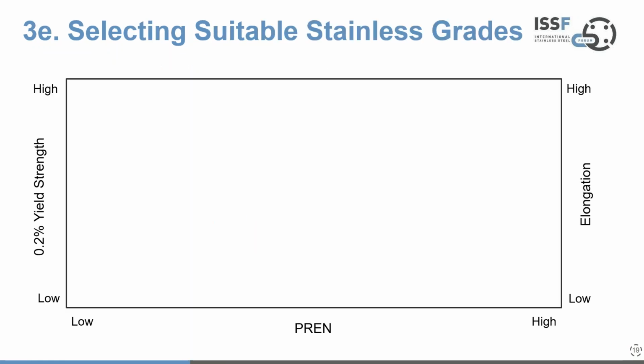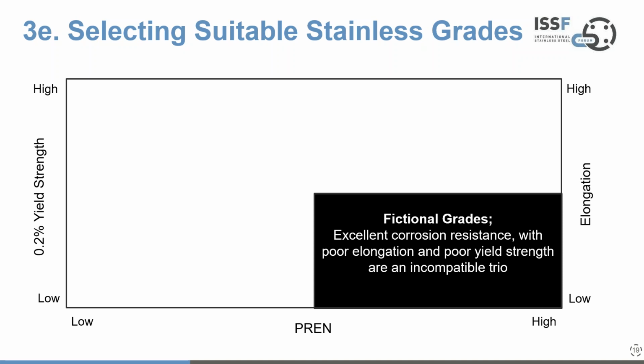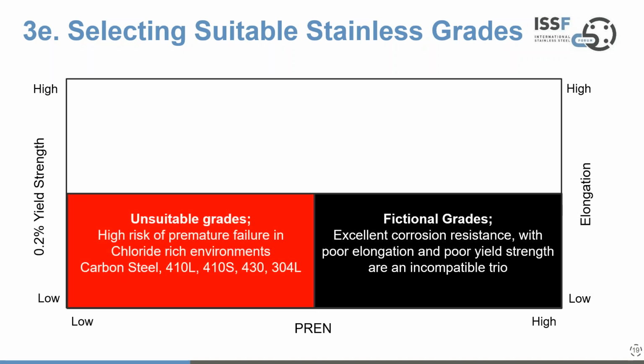So what I'll now try to do is bring those characteristics together in a simple diagram. First and foremost, and this is the same layout as the previous charts, we've got the pitting resistance equivalent number along the bottom, yield strength on the left-hand side, elongation now on the right-hand side. And in the bottom right-hand corner, you would have what I would describe as fictional grades, a combination of excellent corrosion resistance with poor elongation and poor yield strength, which is not a greatly compatible mix of three things. But then in the bottom left, you have what I would term, when you're thinking about particularly bridge building, unsuitable grades. Here you have a much higher risk of premature failure, particularly in chloride-rich environments, and carbon steel sits in there, sure, as well as some of the classic stainless steels.